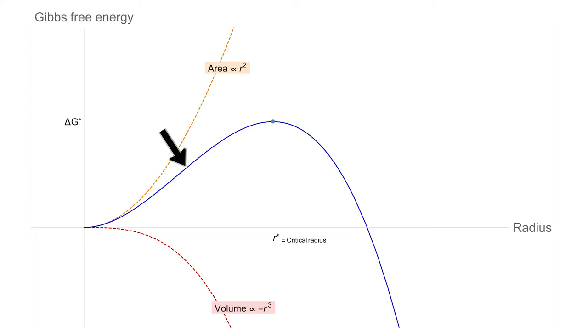So some small sphere of ice that is formed in the water won't last long even though the water is at a temperature below zero degrees Celsius. So when water is supercooled, so it's liquid and it's below zero degrees Celsius, it's in a so-called metastable state. It's in a minimum of the Gibbs free energy but only in a local minimum. It still can get a lower Gibbs free energy if it freezes instead of remains liquid.